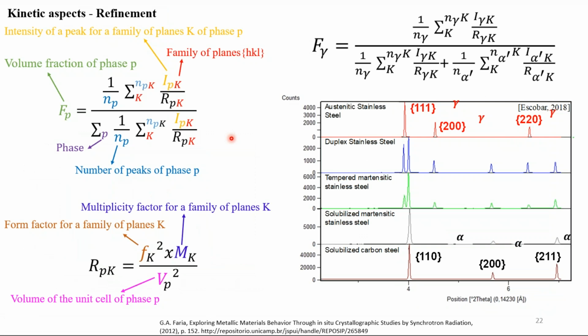Okay, you can do the math with these peaks, with the diffractograms. We have several materials here: austenitic stainless steel, duplex, martensitic stainless steel, other carbon steel, and you can see the position of the peaks, austenite and ferrite, or martensite in some cases. And then you have this equation that gives you the volume fraction of the phases. You are going to have to discover some information about your material, but most of it is within these diffractograms. You need the intensity of the peaks, the weight of the peaks, information of the crystallography of the phase you are analyzing, and then doing that math, you are going to calculate the volume fraction. At least that's the tool we use.